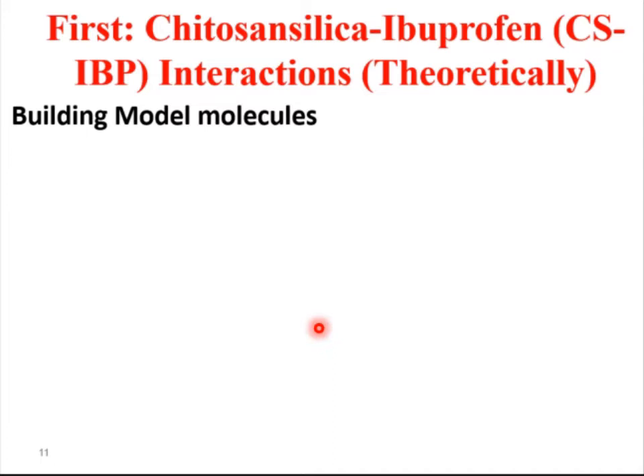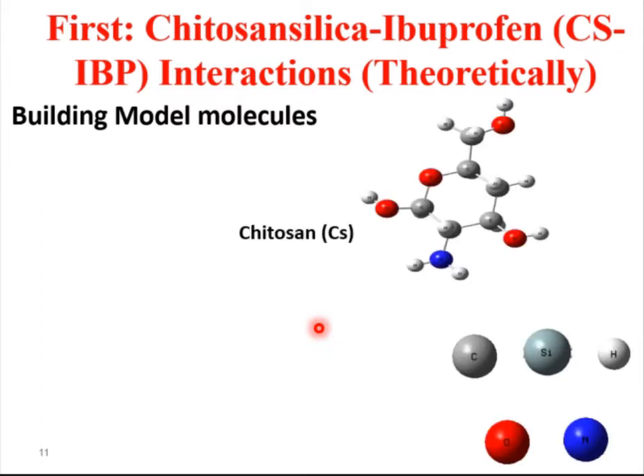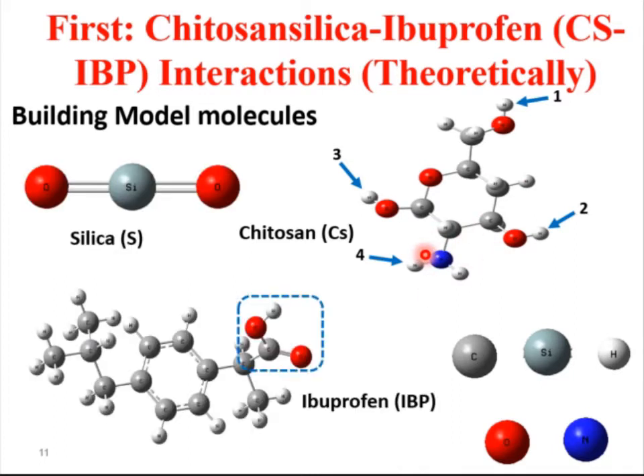Theoretical approach, starting with building model molecules. We have three model molecules: chitosan molecule, which has four active sites, three hydroxyl groups and one amine group, then silica, and finally ibuprofen molecule, which has a terminal carboxylic group. So we have four active sites for chitosan and one active site for ibuprofen, resulting in five interaction possibilities between chitosan and ibuprofen, four physical interactions, and one chemical interaction between the amine group and the carboxyl group forming an amide chemical bond.